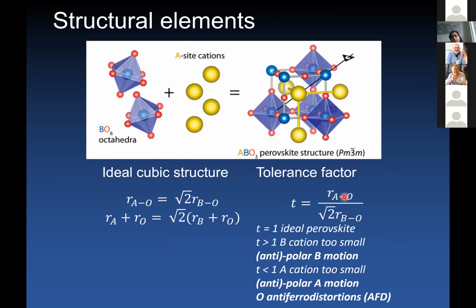But in order to realize an ideal cubic structure, for geometrical considerations, you need the bond length of the A to oxygen cation to be the square root of 2 of the bond length of the B and oxygen. So that's for the ideal case. If you now try to incorporate in the structure a cation that is too small to realize this geometric arrangement, then the system can tolerate this by executing polar or antipolar motions of the B cations. And this is a situation that you often find in ferroelectric type of materials.